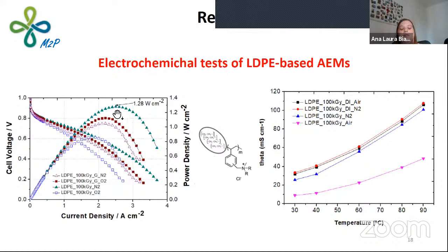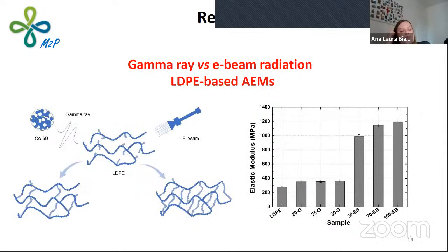And now we are investigating the effects on the stability. Another work, also with LDPE, is investigating the difference of membranes irradiated by E-beam using the pre-irradiation method for grafting and membranes irradiated by gamma ray, in which the grafting step occurs in situ, the simultaneous method. So far, our results point out that we have much more cross-linking being formed during E-beam irradiation than during gamma